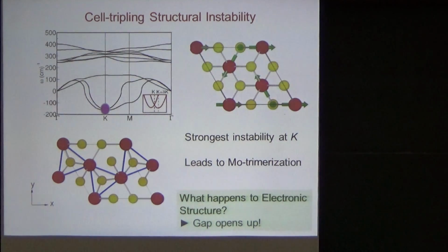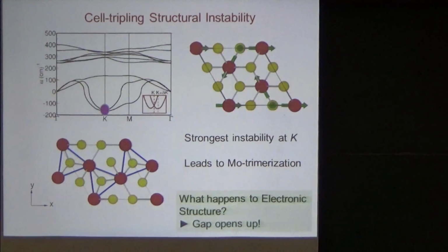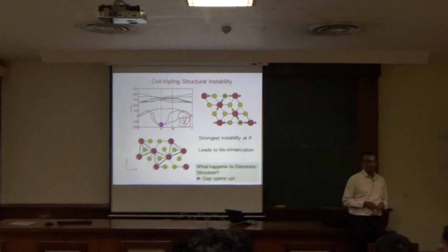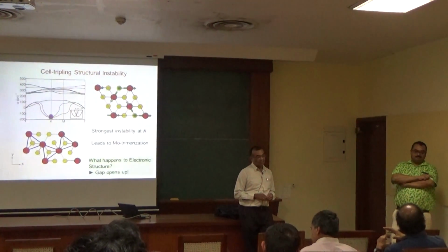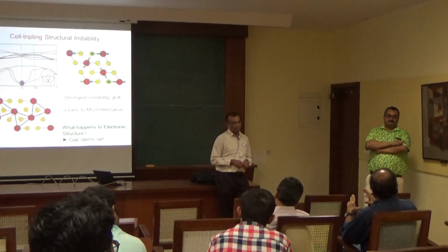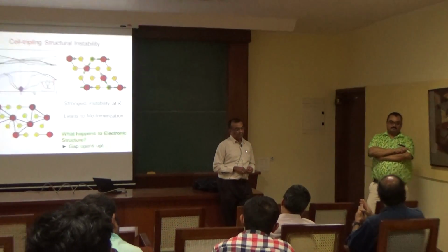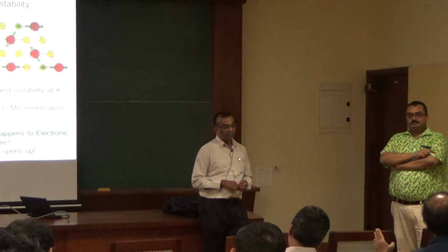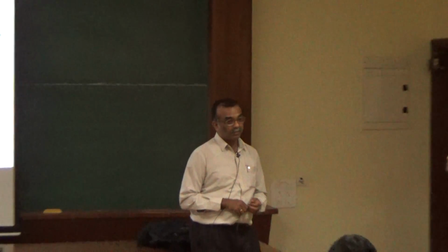Yes. Firstly, a comment on the size dependence. It is not correct to say that the Tc has shifted by 40%. We have not seen the ferroelectric activity vanishing down to some particular size within 40%. It is probably much lower than that, because there are a couple of points which show that the Tc has almost flattened out. We could not measure much smaller particle sizes, so we don't know.